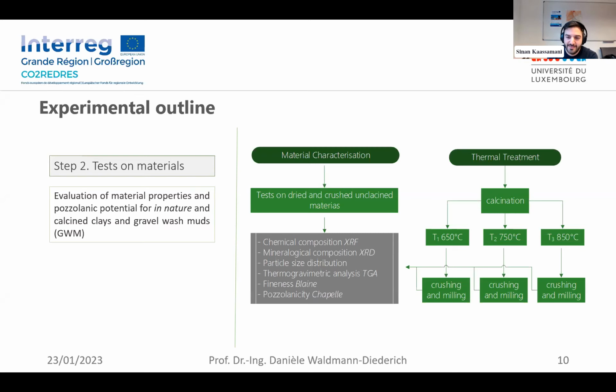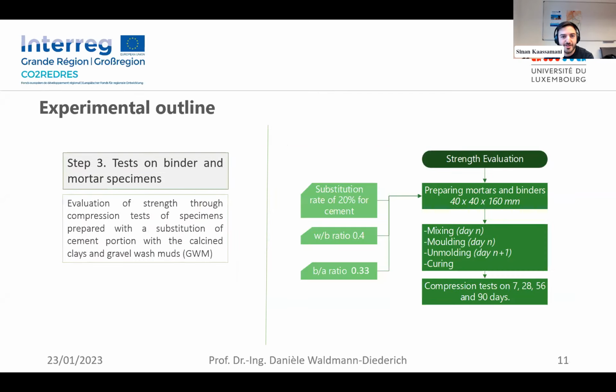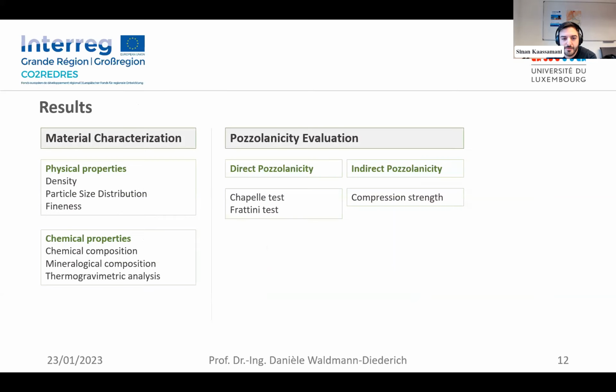And then we studied again the same set of tests for all of them to see actually the differences. And I will show some in my presentation today. So first, after studying this, we also made tests on binders and mortars, to evaluate, of course, strength, compression, as well as tension, but mainly compression here. So we evaluated binders and mortars for 7, 28, 56, and 90 days with 20% substitution rate. And I will present only the results for 90 days, which I will show later.